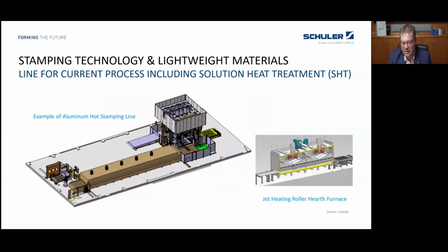So, how does a production line look like for this process? Schuler has also delivered presses for this process. Here you can see the example using a roller hearth furnace with jet heating. On the right side, you can see the principle of jet heating. It's more or less a hot fan, and you blow the hot air on the surface of the aluminum to heat it up quickly, because, like I said, with radiation alone it will be very slow and not very effective.